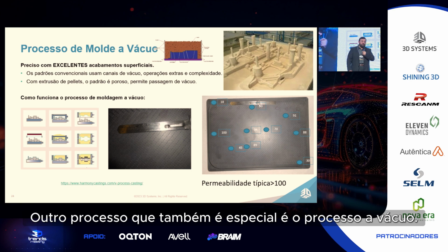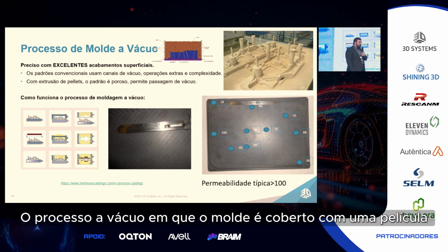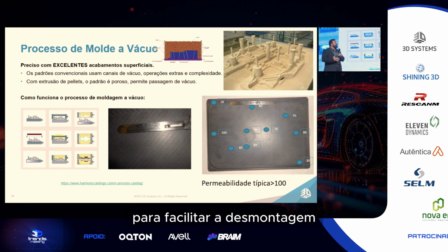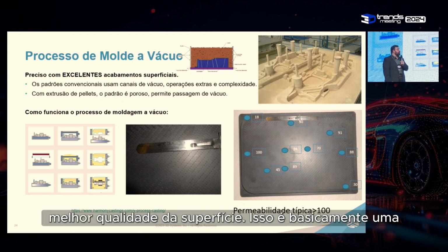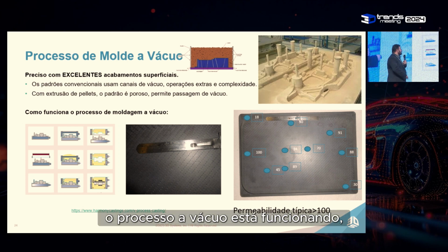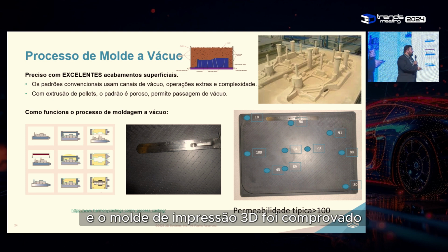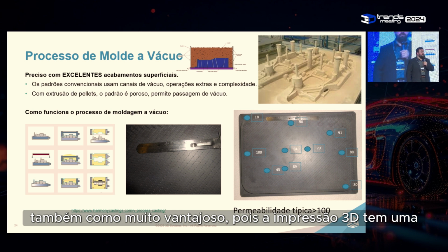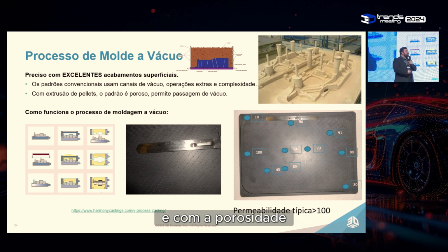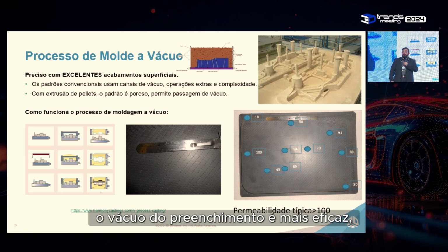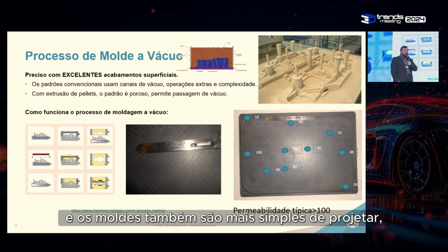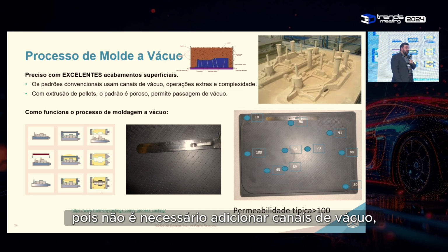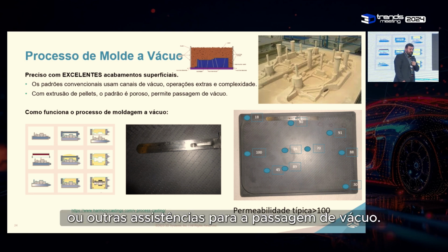Another process that is also special is the vacuum process, where the mold is covered with a film to facilitate the disassembly and also to have better surface quality. This is basically just a simulation of how the vacuum process works, and the 3D printed mold has been proving a lot of advantage, because 3D printing can use porous material, and with the porosity, the vacuum of the film is more effective. The molds are also simpler to design, because there is no need for vacuum channels or other assistance for the vacuum passages.